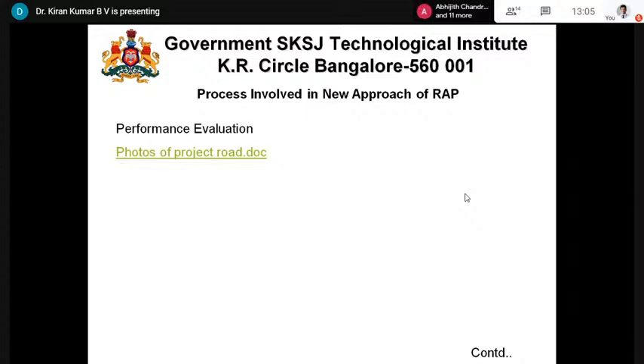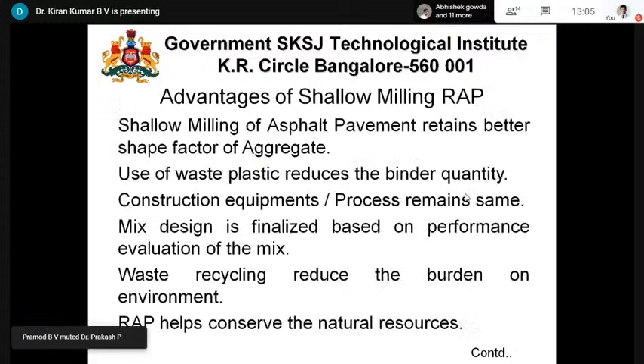So we have done this particular evaluation. After this evaluation, we found that the pavement is intact without any overlay. But the other portions of the pavement where this plastic was not used, where the recycled material was not used, have already undergone an overlay. That was done in the normal course. They did not add plastic. The normal bituminous with virgin aggregates was done, but it has come out. But this is still intact with few failures at the edge because the traffic enormously increased.